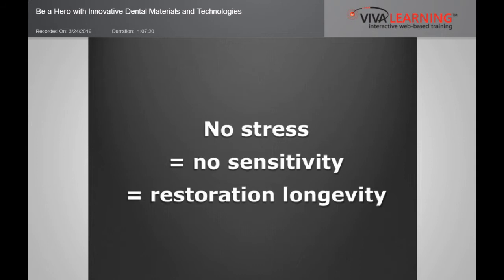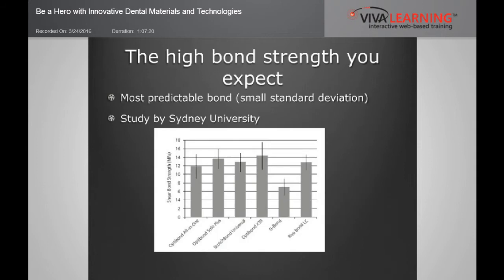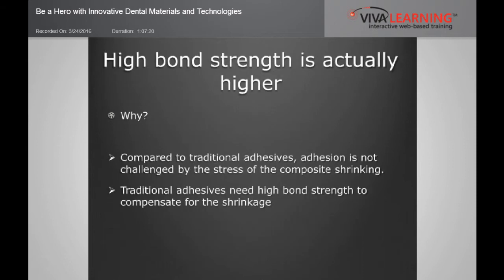But this adhesive, is it a strong adhesive? And again, comparing Rivabond to all those leading resin-based adhesives, Rivabond is in the upper area. So the shear bond strength on dentin is excellent. And in fact, it's even higher. Why? Because traditional adhesives need that high bond strength to compensate for shrinkage. And even if you have an extremely high bond strength, if it pulls on your margin, you may get a cohesive fracture, and you will get that thin white line around your restoration.